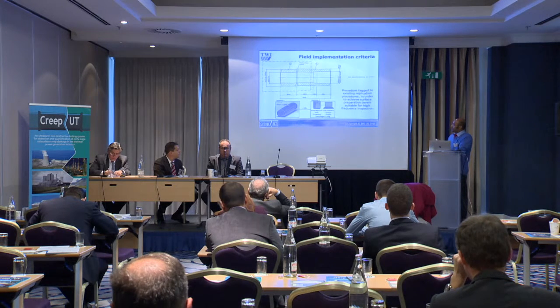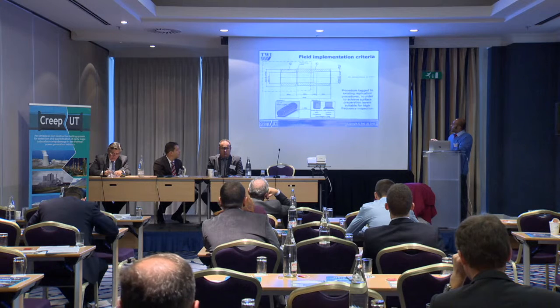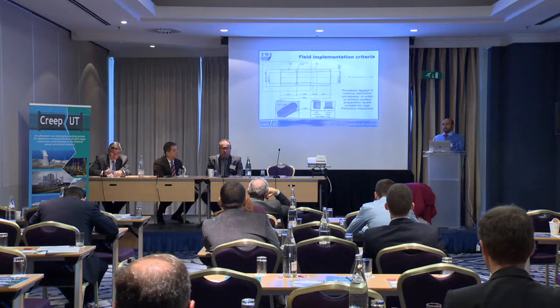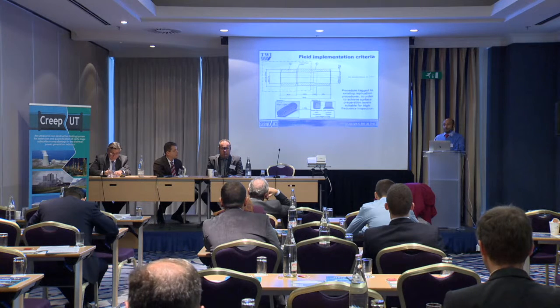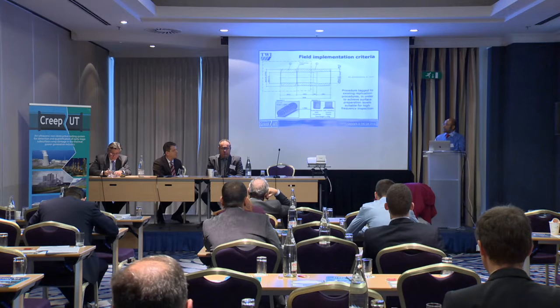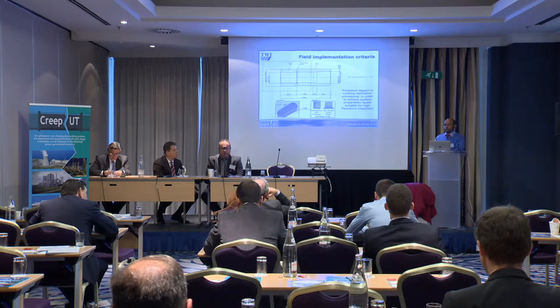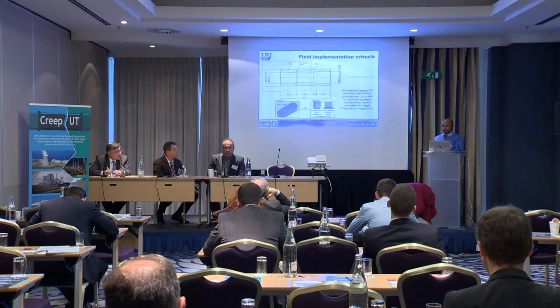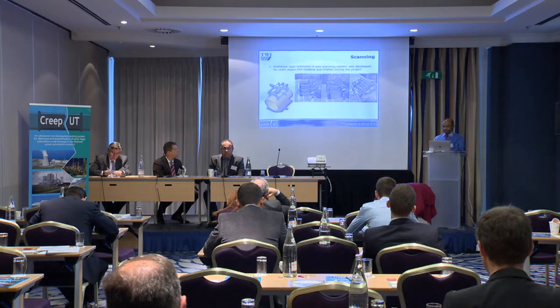And what we also wanted to do was to tag our inspection procedures to the replication procedures, because at 25 to 30 odd megahertz, we needed to achieve surface conditions which were basically being applied by field metallography operators. So we can just go behind them and then implement the UT. So the idea was that the replication will look for surface indications, and then we will support that with subsurface indications using a UT system.